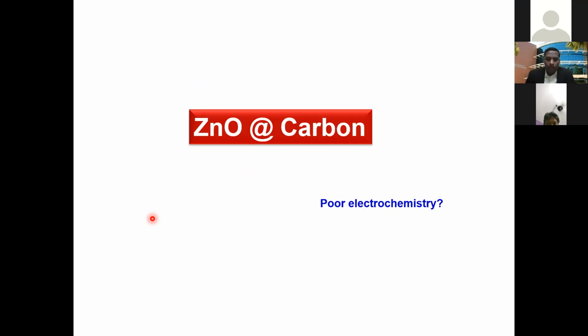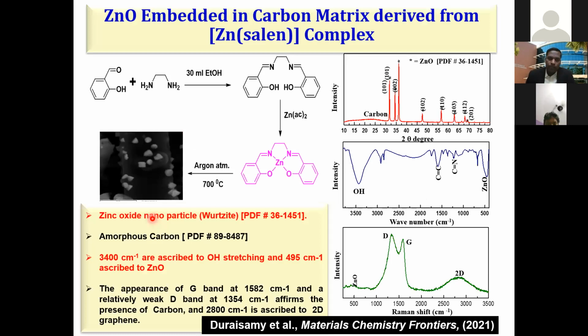And for quite some time, zinc oxide has been thought of as having very poor electrochemistry. As we all know, it doesn't get oxidized or reduced easily. And we tried to make a complex of zinc using the same salen ligand. Following a similar procedure, by firing at 700 degrees in argon atmosphere, we could get the zinc oxide.